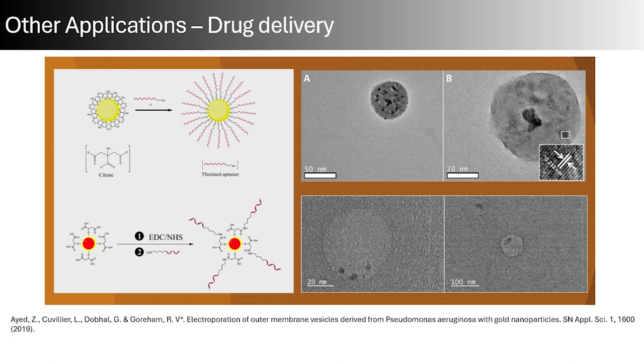And what we were able to do, if we had nanoparticles, such as gold nanoparticles that were less than 10 nanometers, and then put those in the solution with the extracellular vesicles and then zap them, the pores would be big enough for those nanoparticles to go inside. And that's what we see here. So we've got 50 nanometer extracellular vesicles and about 5 to 7 nanometer gold nanoparticles.